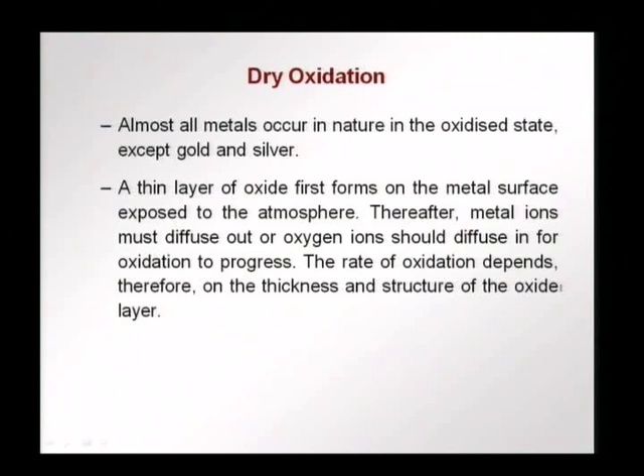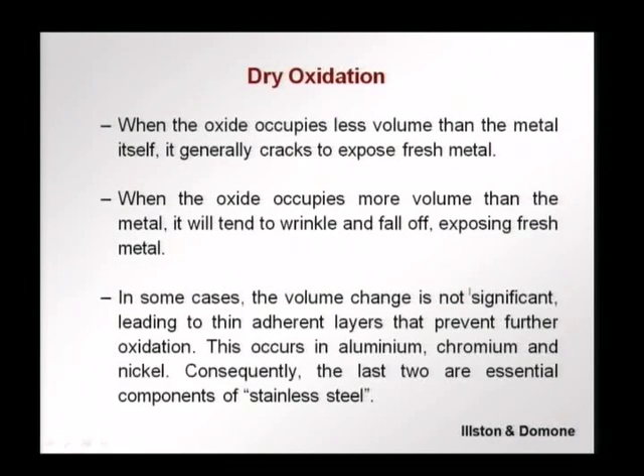The rate of oxidation therefore depends on the thickness and the structure of the oxide layer. If it is thicker, then oxidation will be slower, and if the structure is very impermeable, it does not let anything in or out, then again the rate of oxidation is lower. When the oxide that forms has less volume than the metal itself, then it shrinks and cracks. This exposes the fresh metal to oxygen, and further oxidation can continue to occur. Sometimes the oxide has more volume than the metal from which it formed, and there it will delaminate, it will try to stretch, wrinkle and fall off, again exposing fresh metal by creating a new surface.